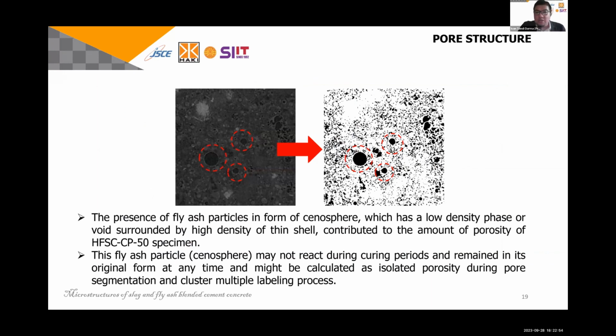Here, as I mentioned before, we will have a cenosphere particle. The presence of fly ash particles in the form of cenosphere, which has a low density phase or void surrounded by a high density thin shell, contributes to the amount of porosity in the fly ash specimen. So maybe this is the answer why in some research we found that a fly ash specimen has higher porosity compared to the OPC specimen. You will have the cenosphere and it contributes to the porosity.